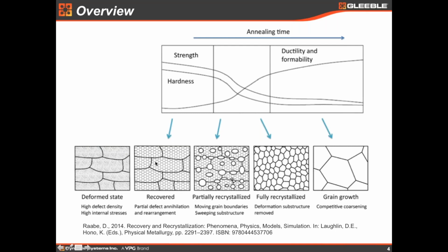As we start the annealing process, or increasing the temperature, we see that there is a decrease in strength and hardness, and this is due to the annihilation and rearrangement of the dislocations, forming the subgrains. You can see the subgrains here inside the grains, and after that we have the nucleation and growth of the recrystallization process. So in this case, we have a high angle grain boundary moving over the work hardened matrix, moving over the subgrains,